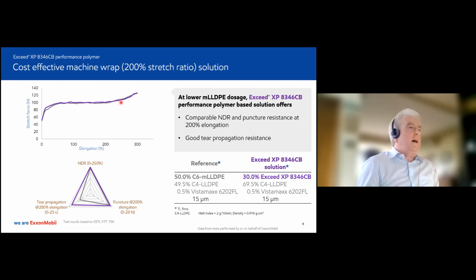And the importance of that is that beyond that NDR, you start getting strain hardening kicking in, which means the film becomes a little bit weaker, and it can't stretch very easily without breaking, perhaps, if it gets too high. And if you stretch below the NDR, then you get premature stretching of the film and you lose holding force. So really the objective is to try to target the NDR on the film that you make.